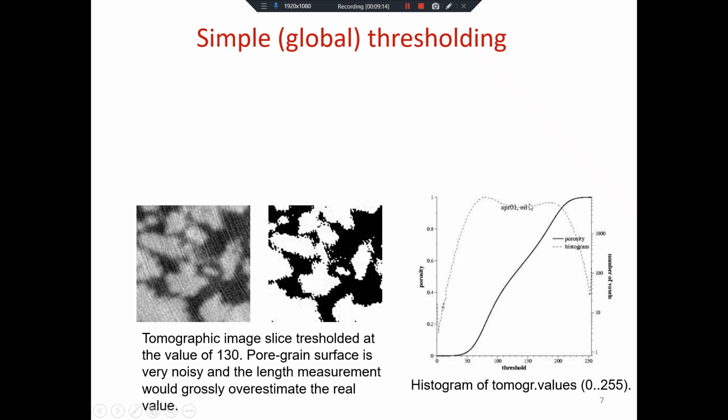So if you have a histogram that looks like this, no threshold will work. A lot of times in segmentation, because thresholding is so easy, a lot of people spend a whole lot of time finding what I call a magic threshold in order to segment the image. No, this is not filtered correctly. No magic threshold will help.